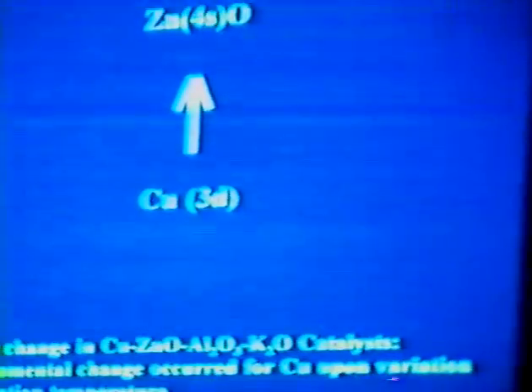This was probably suggested by people before: a transition from the copper to the zinc oxide conduction band is responsible for the black color. So when we see the color change in our copper zinc aluminum potassium oxide catalyst, it probably means an environmental change occurred for the copper upon the variation of the reaction temperature.